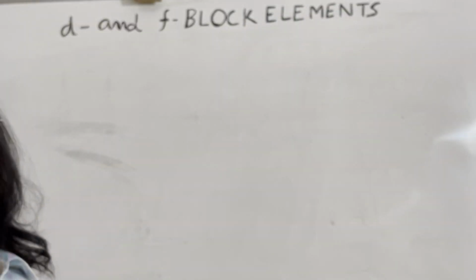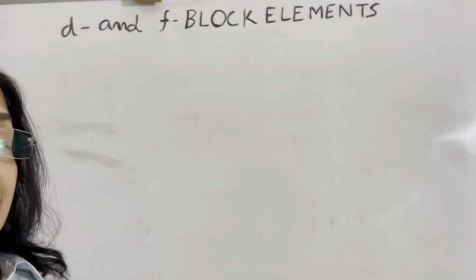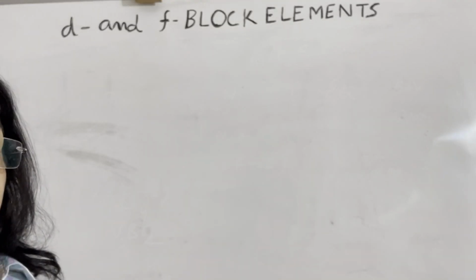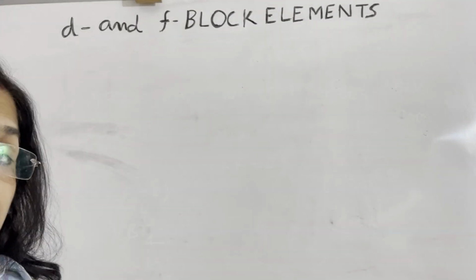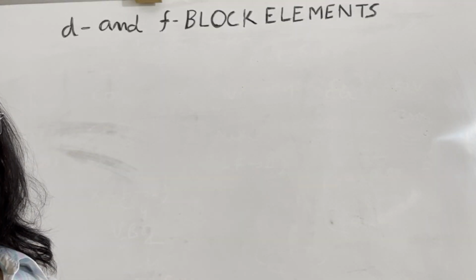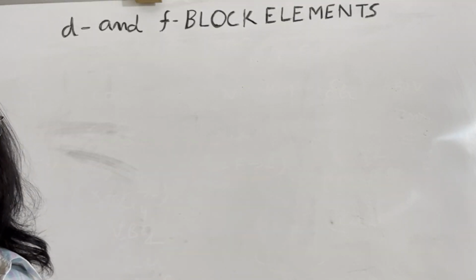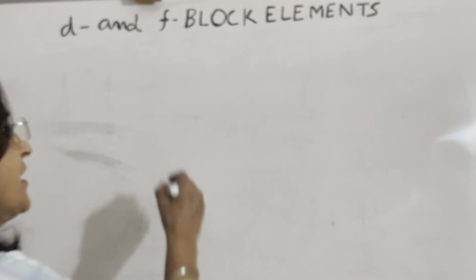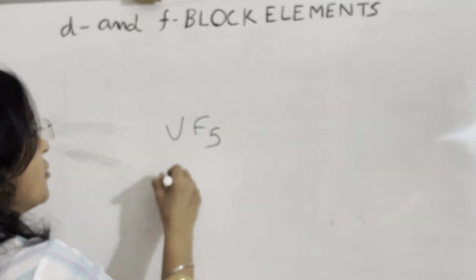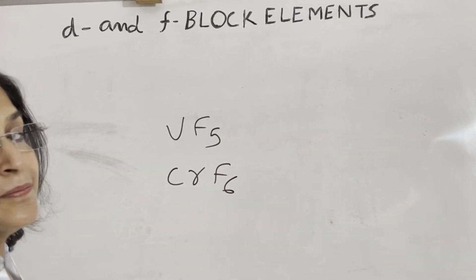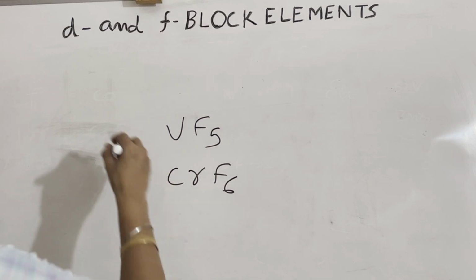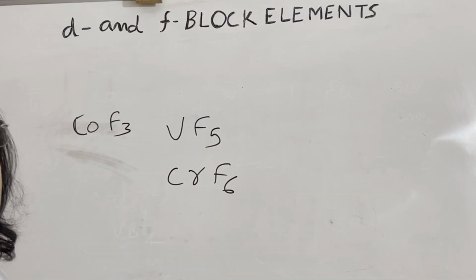In the lower oxidation state, fluorides are unstable. The higher oxidation state of these transition elements are stable in the case of fluorides. Fluorine is highly electronegative. Second, higher lattice energy in metal fluorides. Third is higher bond enthalpies. For example, in vanadium pentafluoride, chromium hexafluoride, bond enthalpies are very high. In the case of cobalt trifluoride, lattice enthalpy is very high.